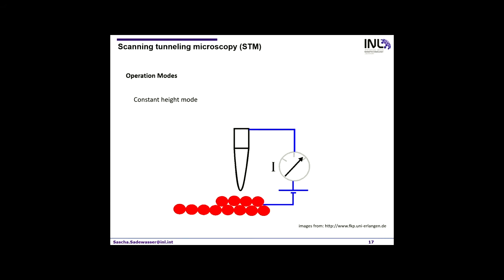And there's another way to do this, which is to use constant height mode. Here you're actually keeping the tip always at the same height, and then you're measuring the current. So if you're on the lower step, you have a lower current. On the higher step, you have a higher current. This is much faster because you don't need to do the feedback, so you don't have a controller to do the feedback. But you only get relative information. So you cannot really know how high your step actually is.